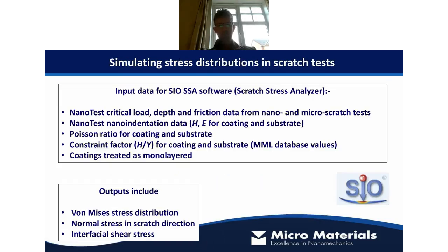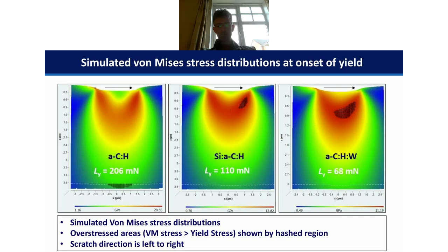So we can simulate that with another optional module in the nanotest, which is this integrated SIO software, in this case the Scratch stress analyzer, and we input the data from the indentation testing. Constraint factor is also very important, and this allows us then to simulate the stress distributions that are developing in these scratch tests, and we can get information about the von Mises stresses, the normal stresses, and the interfacial shear stresses. So this is an example here looking at the von Mises stress distributions at the onset of yield. In each of these cases, the scratch direction is from left to right, illustrated by this arrow here.